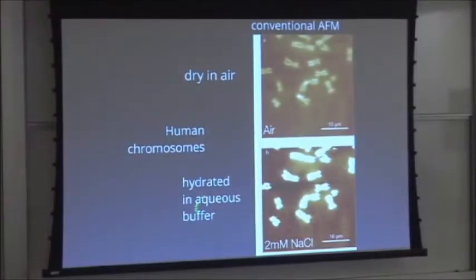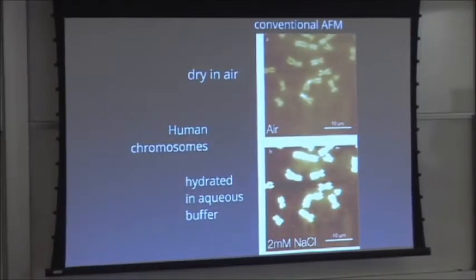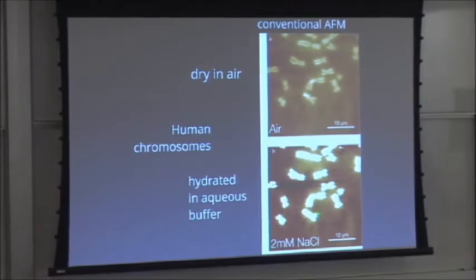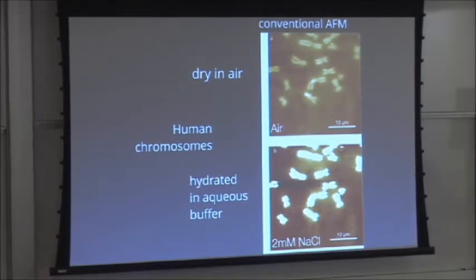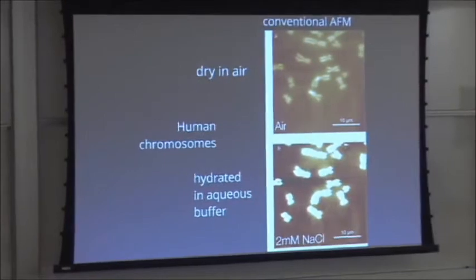Here are some human chromosomes taken with conventional tapping mode AFM. Then we've hydrated them in buffer, and they've swollen by a factor of 5 from the dry down state. So now we've got a huge structure. Yeah? So if we're just scanning this tip over the surface, surely when it hits half a micron high, soft, gel-like chromosome, it's going to damage it.